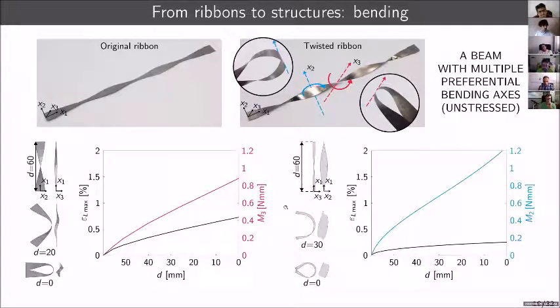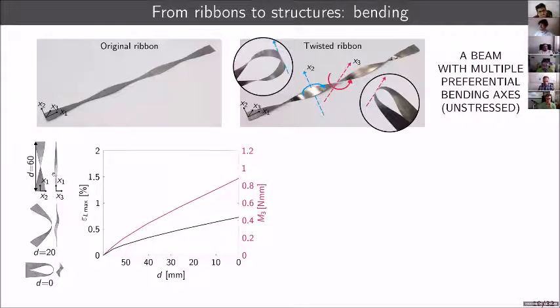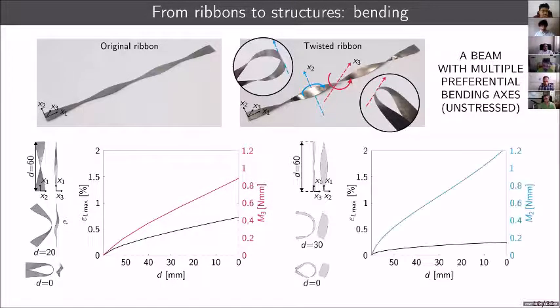One interesting thing that you can see over here is that once you bend this hinge, this is actually not a perfect in-plane hinge. Because you take your hinge, you bend it, and there is actually, as you can see over here, an out-of-plane deformation of the hinge, which can be seen as a nuisance or as something to potentially exploit in order to obtain more complex deformation patterns in-plane and out-of-plane. In this case, you see the bending of the wide face about X2, as you can see over here. And also in this case, we don't exceed the elastic limit.